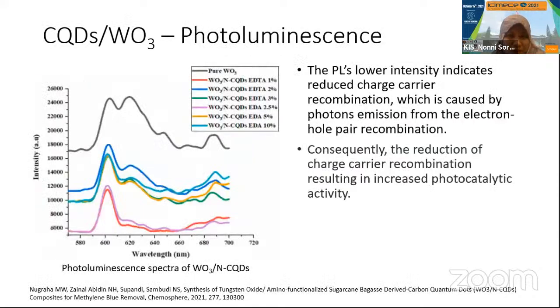Okay. In the case of photoluminescence, what we have is a decreasing photoluminescence spectra when we incorporate the carbon quantum dots into the matrix of the tungsten oxide. Based on the reading that we did, when we have a lower photoluminescence intensity, it can indicate that the recombination of the charge can be reduced. Since the recombination of charge can be reduced, it's good news, meaning that if the recombination is reduced, then more reduction and oxidation reactions can happen on the photocatalytic material. Okay, but we have to prove it with the experimental result.